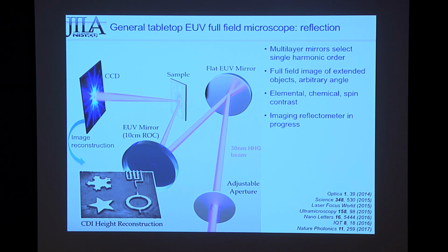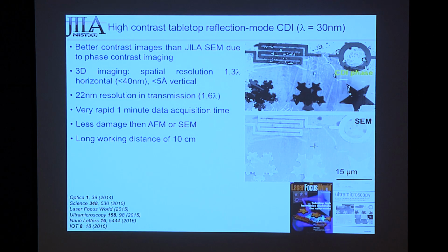As somebody who has worked in the X-ray region for a long time, the good and the bad thing about refractive indices in the EUV is that they're super sensitive to any contamination. If you have a fraction of a monolayer, your EUV index will change, but that's great because you can turn that into very high contrast imaging. And in fact, it was this image that made us think that the technology was good.